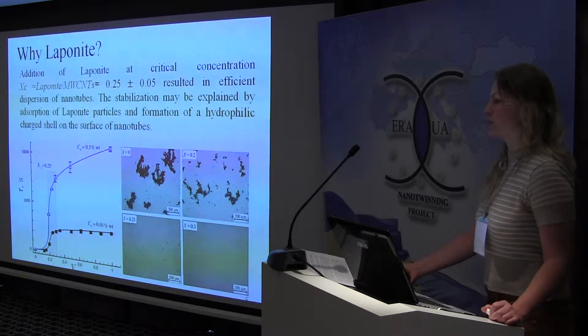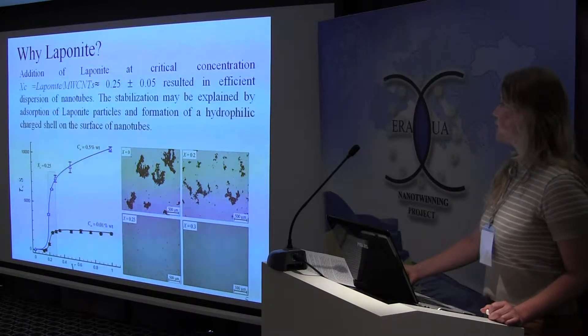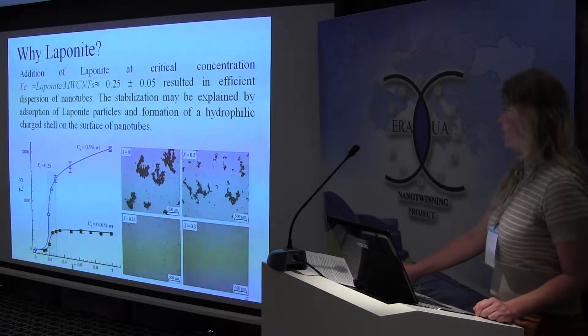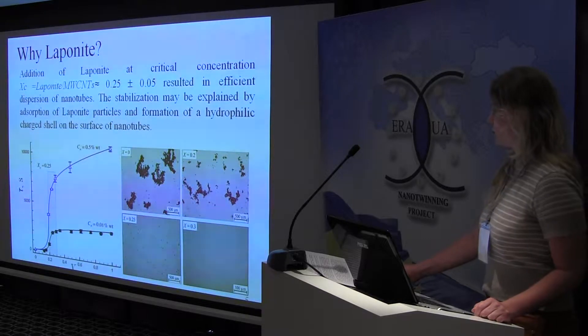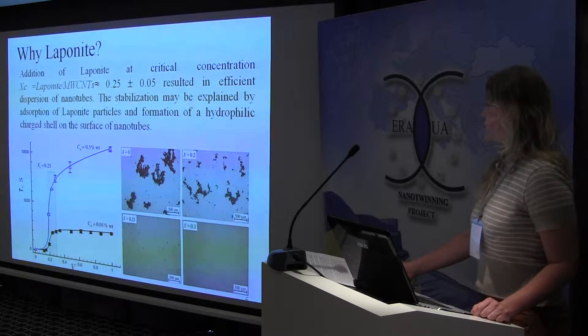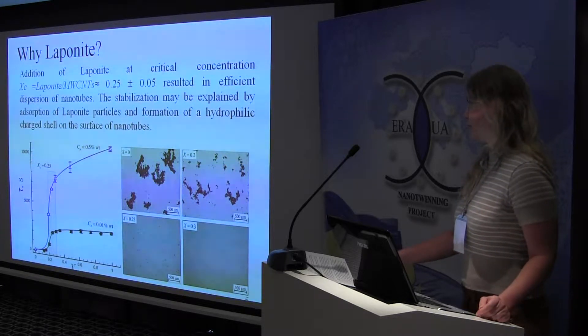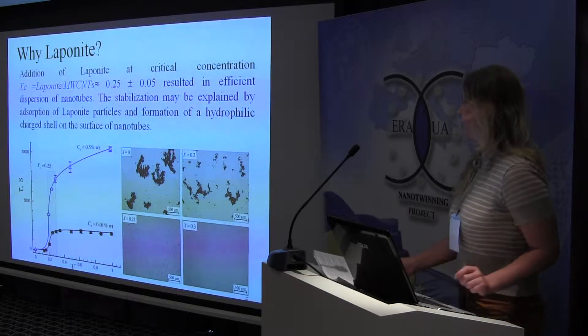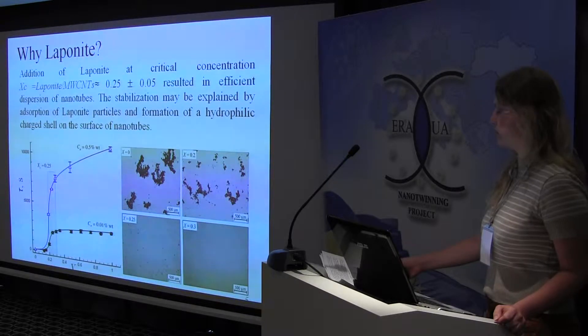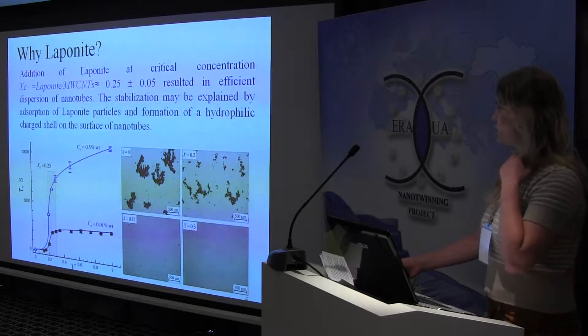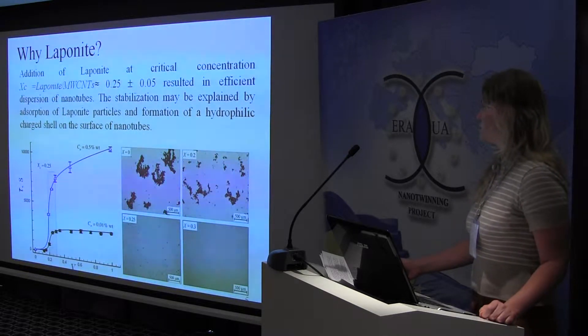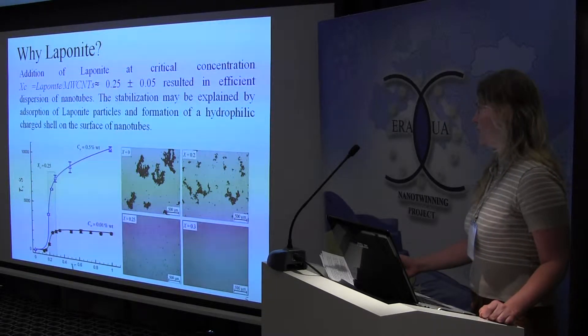The stabilization may be explained by adsorption of laponite particles and formation of a hydrophilic charged shell on the surface of nanotubes. This figure demonstrates the effect of laponite-to-carbon-nanotube ratio on suspension stability time. The suspension is practically unstable at ratios lower than 0.1 mEq, and shows an abrupt increase at the critical concentration of 0.25 mEq for both diluted and concentrated solutions. Concentrations above 0.3 mEq result only in minor additional stability.